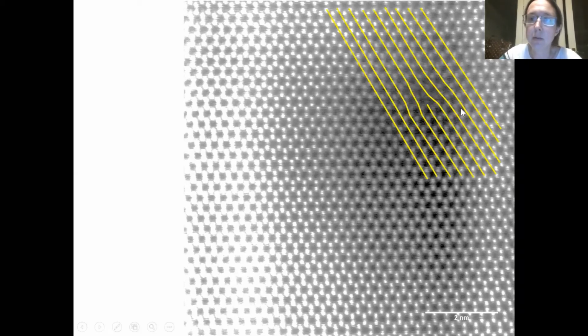If I show up all the atoms in a gallium nitride crystal, the dislocations become a bit more difficult to spot. So actually here we're mostly seeing the gallium atoms. They're easier to image in the transmission electron microscope. And again, we're looking down the end of columns of atoms that extend into the page. But this is a gallium nitride crystal imaged at atomic resolution. It's very characteristic, these beautiful hexagonal rings of atoms. This is the sort of shape you get in the crystal of gallium nitride. And it's impossible, I think, without spending a great deal of time for you to spot the dislocation. But I'll draw it in for you. It's just over here, and we can see its atomic structure.